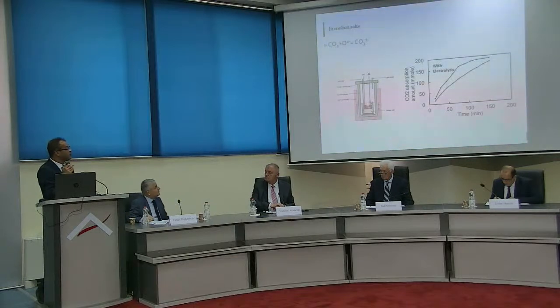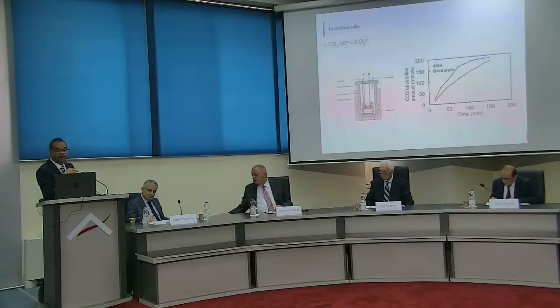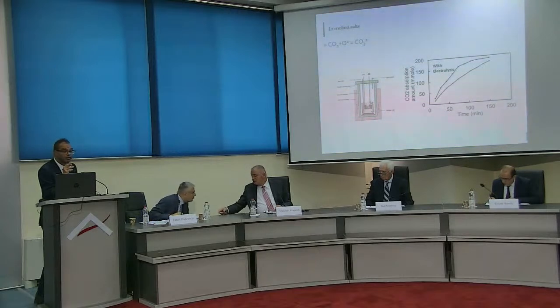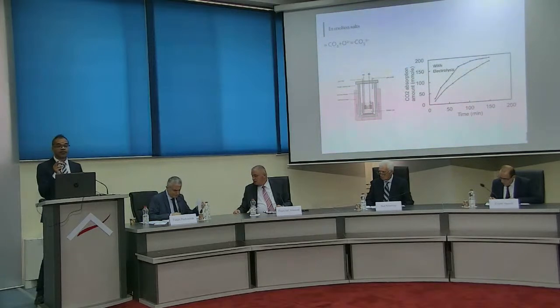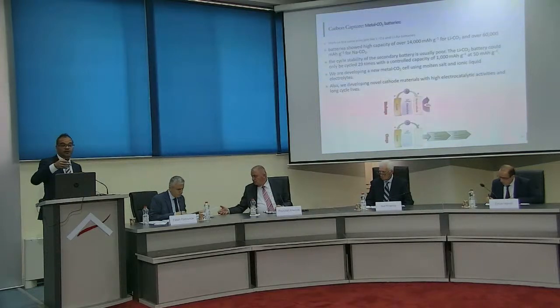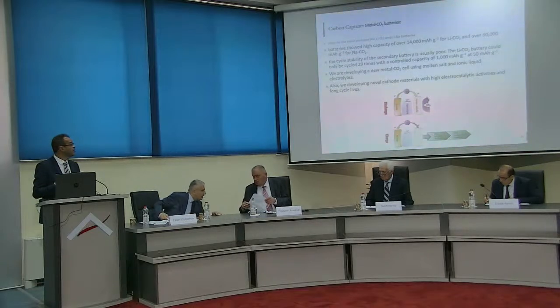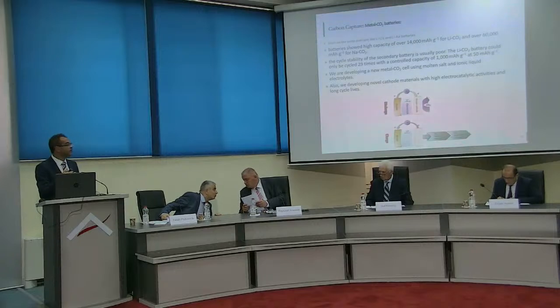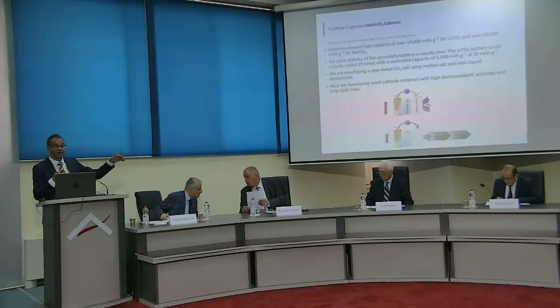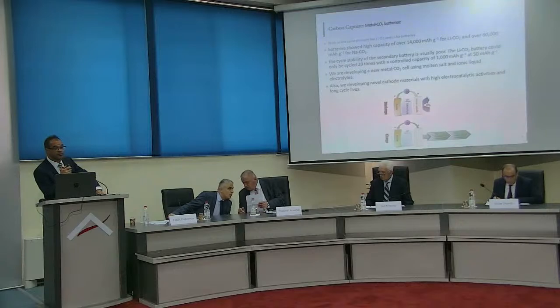We did lots of work, including using electrolyte made of molten salt, because that simply improved the capacity of the battery and also removed lots of kinetic problems on the cathode. The problem with the cathode, with the catalyst, is that you form lots of carbonate on it, and this carbonate blocks the battery after a while. To avoid that, molten salt simply dissolves this carbonate layer or oxide layer straight away, improving the capacity of the battery.